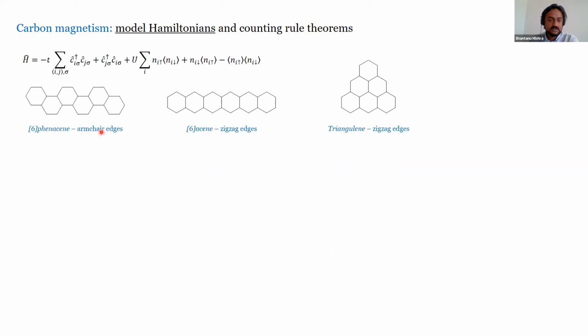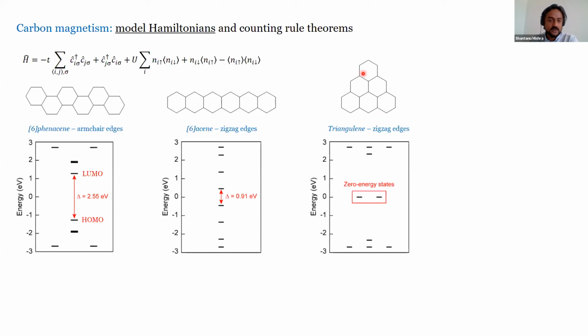So the first is a phenacene, which has armchair edges. The second is an acene, which has two zigzag edges on opposite ends. And the third is triangulene, which has a complete zigzag topology on all three of its edges. And if one only applies the tight binding Hamiltonian, then you see that the phenacene has a pretty large HOMO-LUMO gap. For the acene, which has zigzag edge, the HOMO-LUMO gap shrinks to about 1/3 of its value. And finally, for triangulene, you see that it becomes a zero gap system.